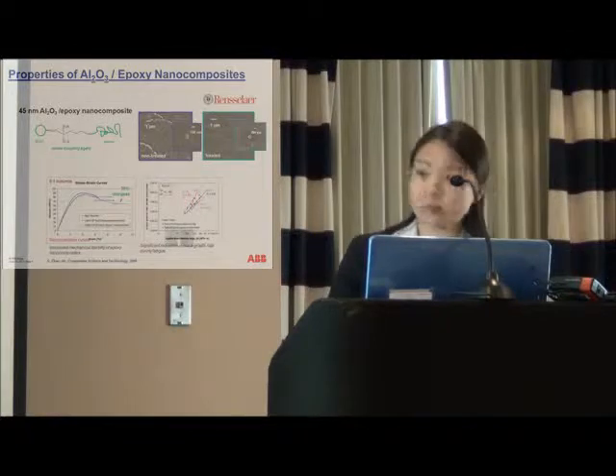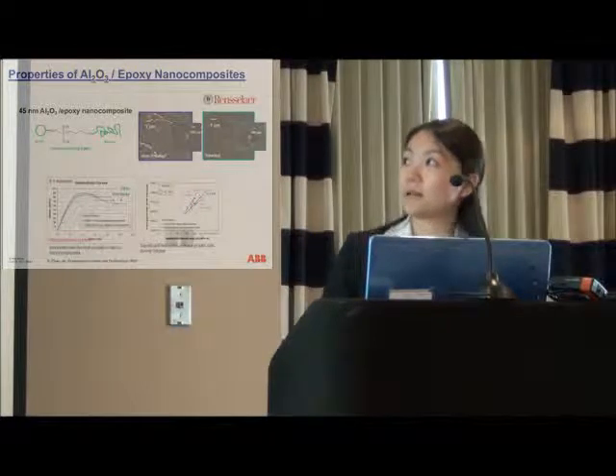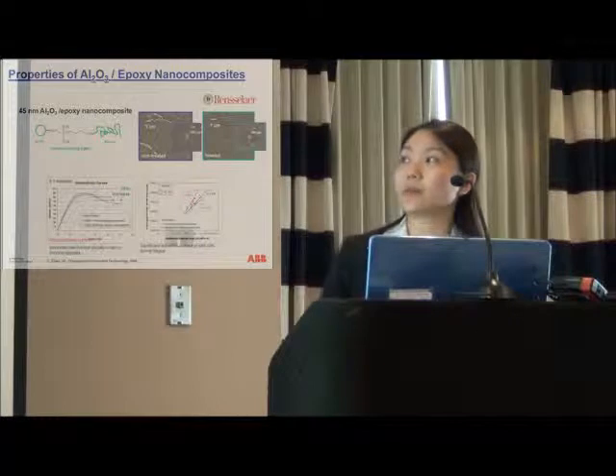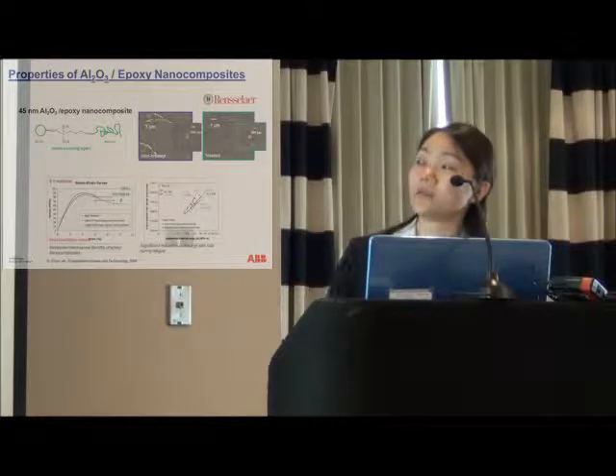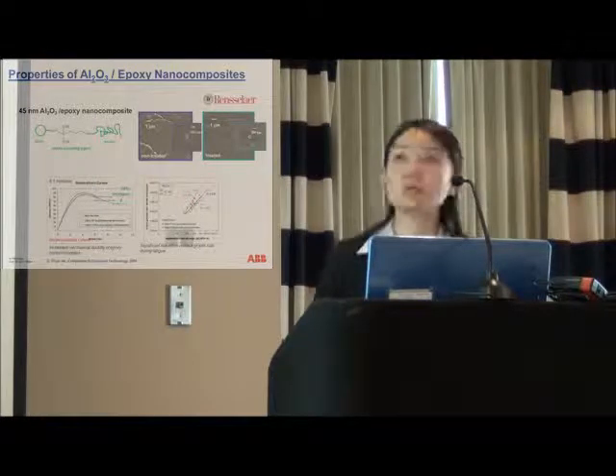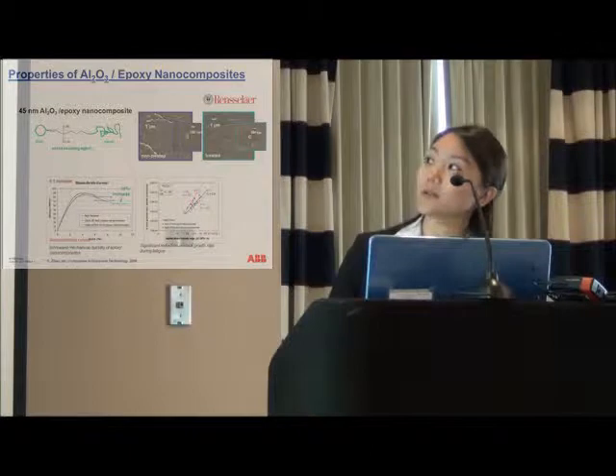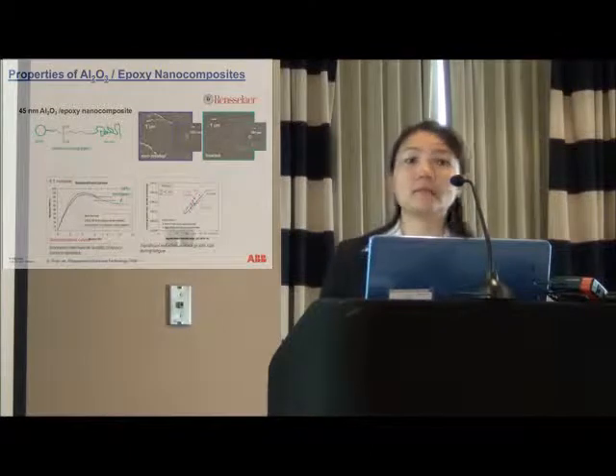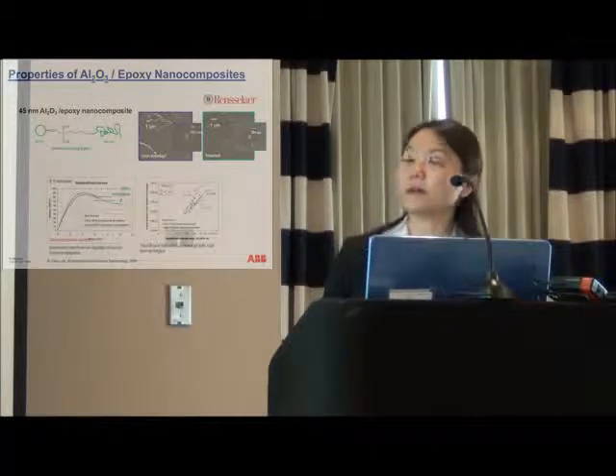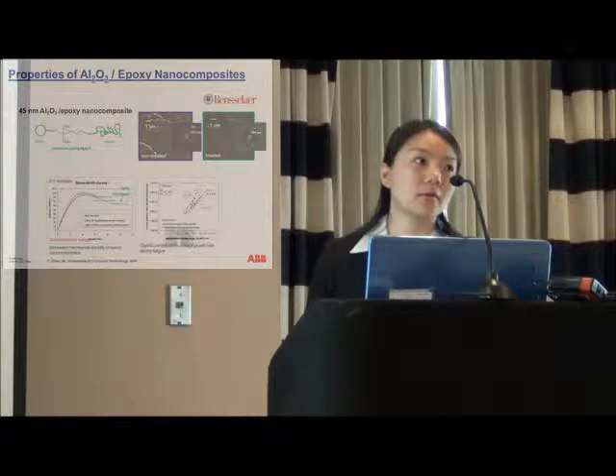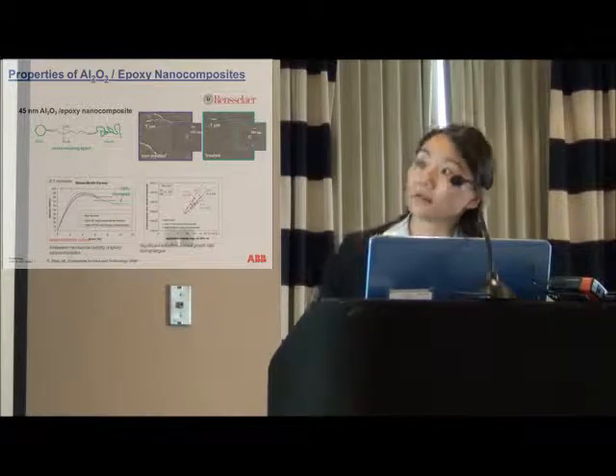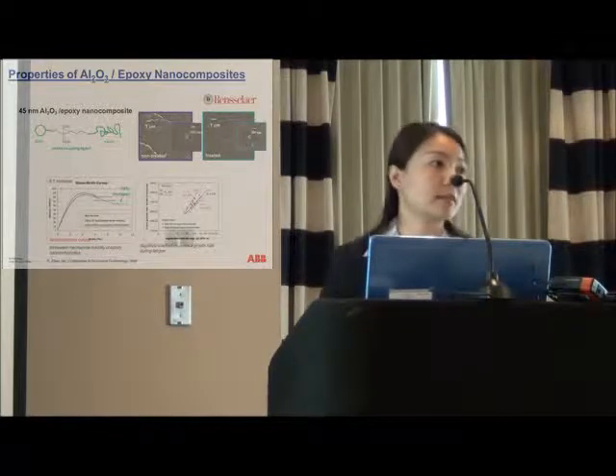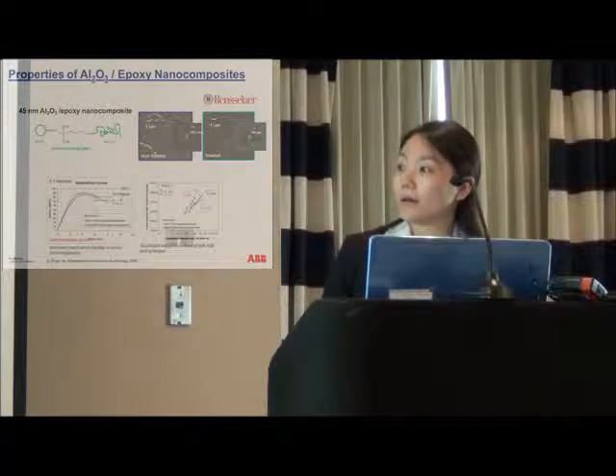In these two SEM pictures, you can see the blue one is the particle-filled epoxy without any surface modification on the particle, and the green ones are the treated particle-filled epoxy, where you get a stronger interface between the particle and the matrix. The surface modification we used was silane at the time.